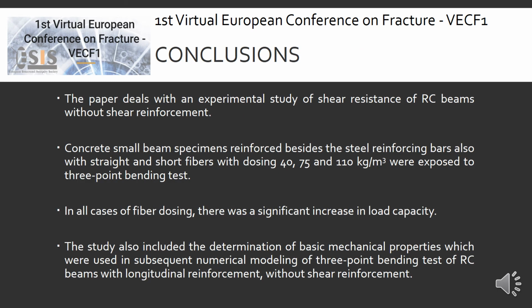Conclusions. The paper deals with an experimental study of shear resistance of reinforced concrete beams without shear reinforcement. Small concrete beams with reinforcement bars, also with straight short fibers with dosage 40, 75 and 110 kg per cubic meter, were exposed to a 3-point bending test. In all cases of fiber dosing, there was a significant increase in load capacity. The study also included the determination of basic mechanical properties, which were used in subsequent numerical modeling of 3-point bending tests of reinforced concrete beams with longitudinal reinforcement.